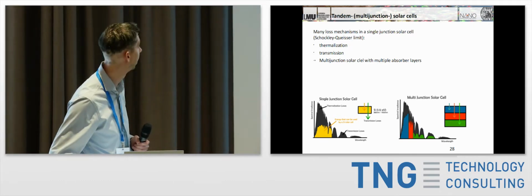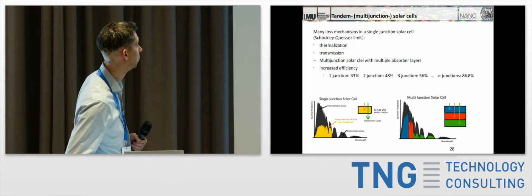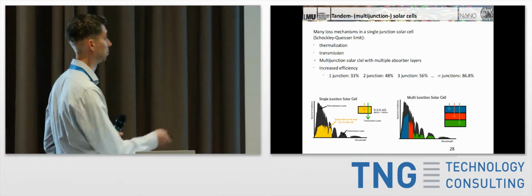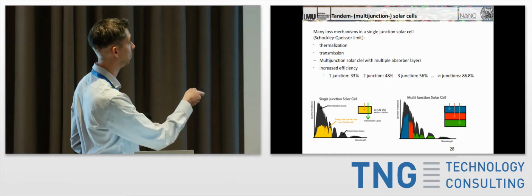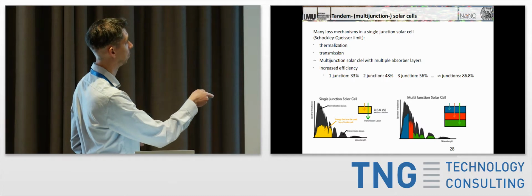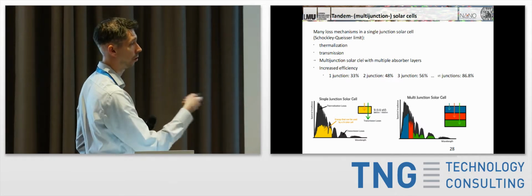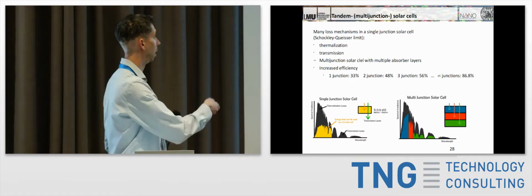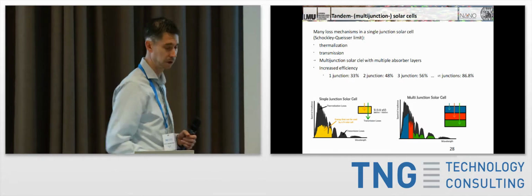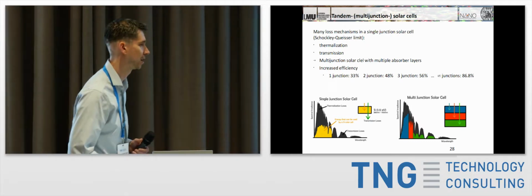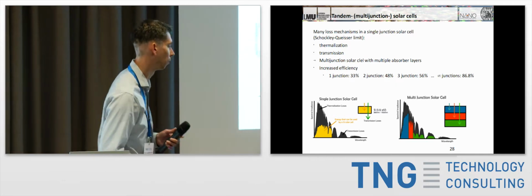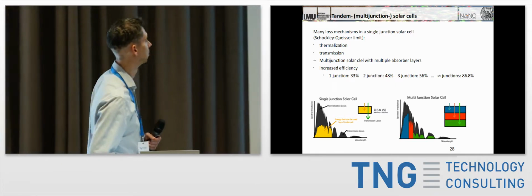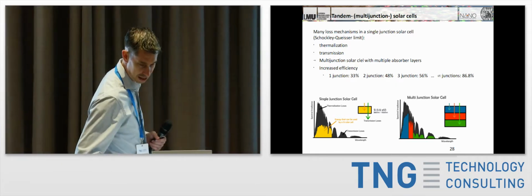usable electric energy. And so now if you look at the actual efficiency, the theoretical maximum efficiency, for a single junction I said was 33%. As you increase the amount of junctions using only a second absorber material, you're already at about 50% of the light. And then it increases on until technically if you have infinity junctions stacked on top of each other, you could absorb 87% of all the light. Obviously it's not quite feasible to actually do this. All right, so has this been done?